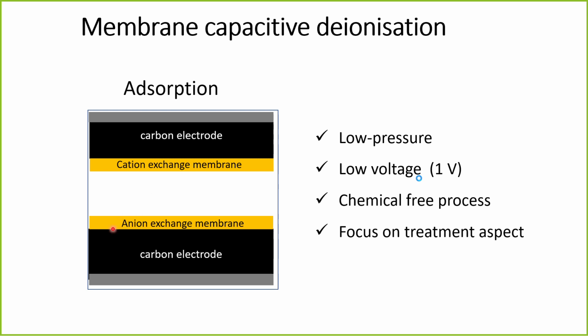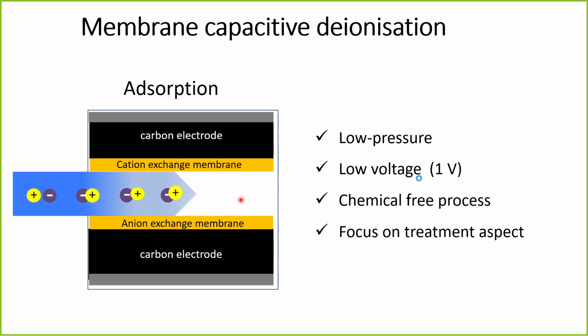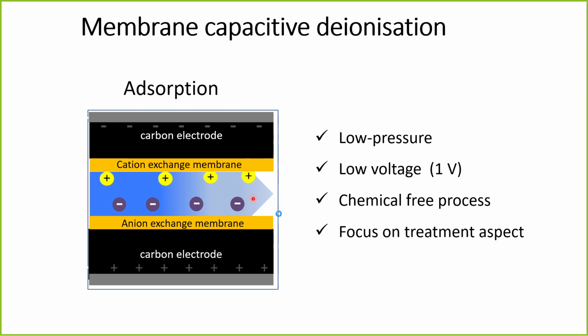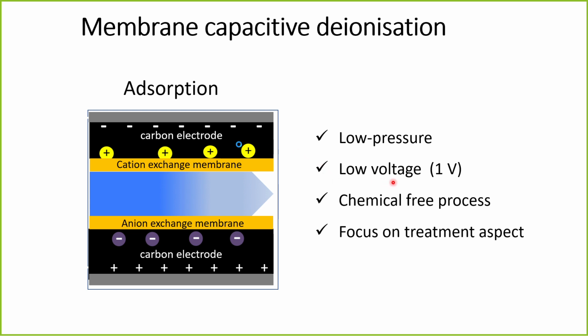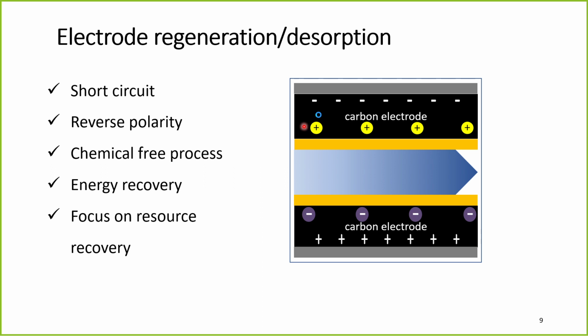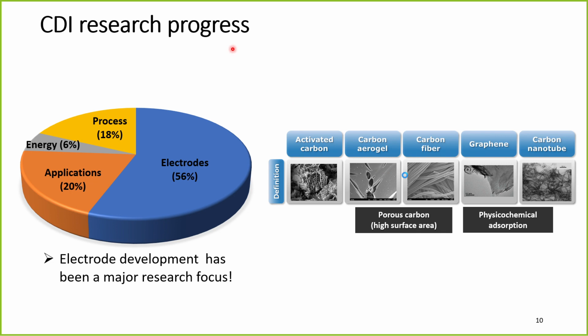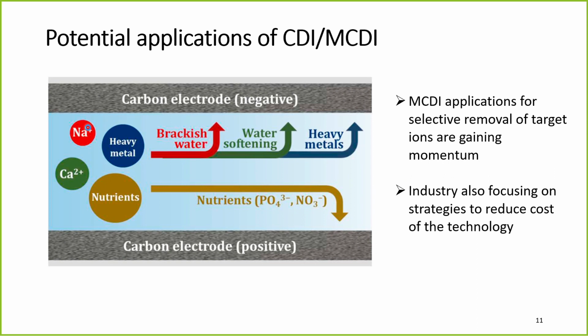We just attach the cationic membrane and anionic membrane to pass through your ions, and positive and negative ions can be collected at this electrode using very low voltage and low pressure, chemical free, and then this can be separated, and we can also have a desorption stage. Using short circuit and reverse polarity, or chemical free process and energy recovery, and also focusing on resource recovery, can be achieved with this MCDI system. There is a lot of research going on to develop better electrodes, such as carbon aerogel, graphene material, or MXene, which can be utilized as good electrodes. Also on the application side, energy saving as well as processes. And this is the application.